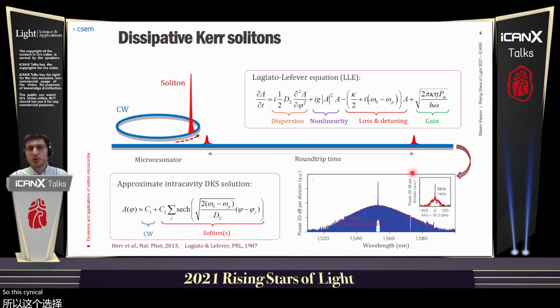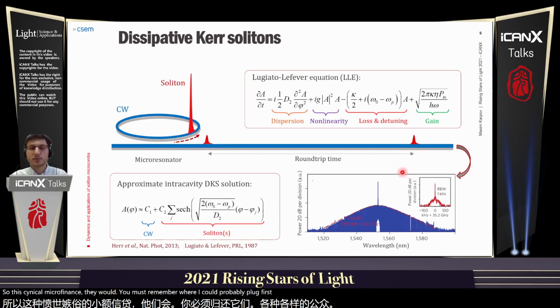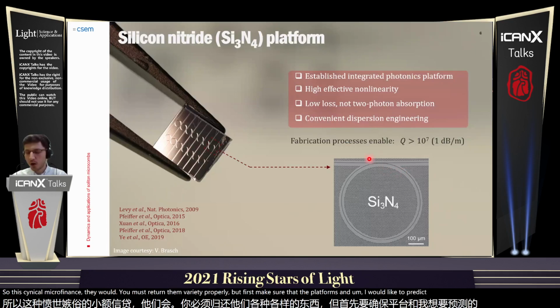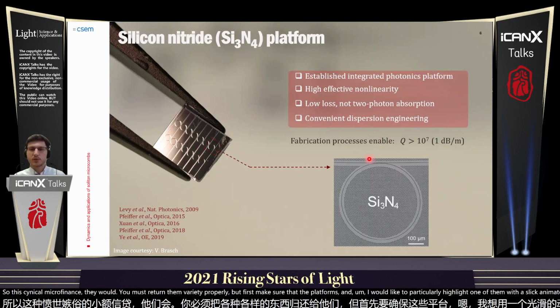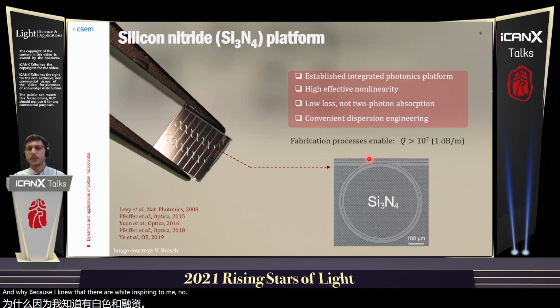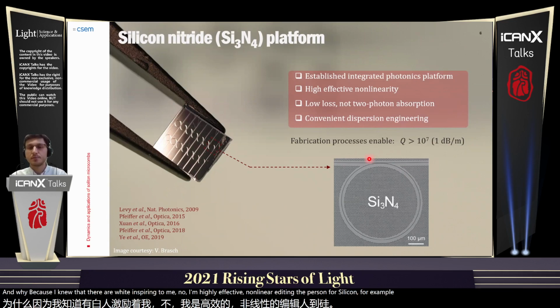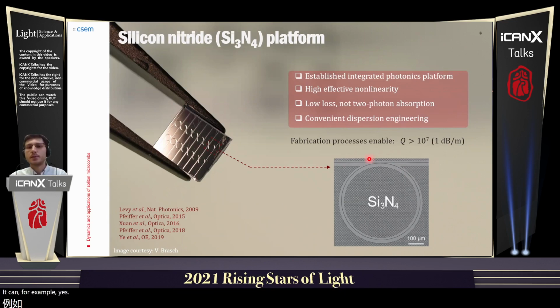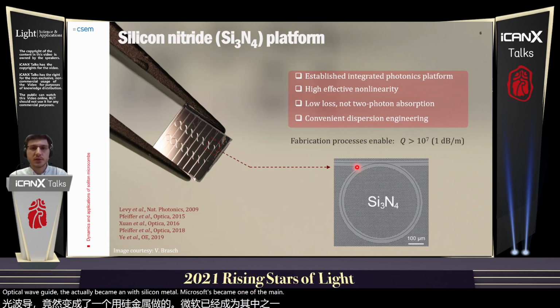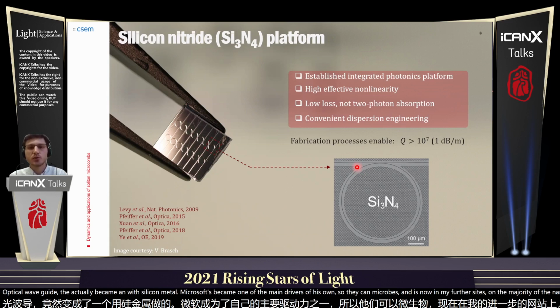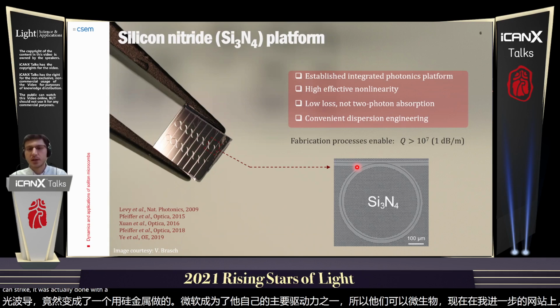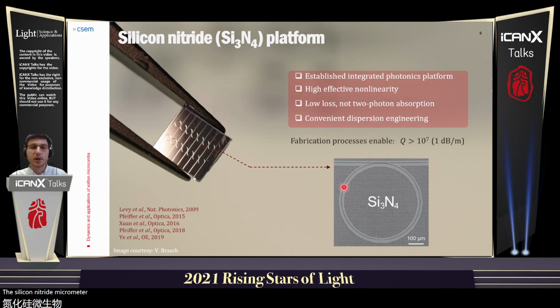So these soliton microcombs were demonstrated in a variety of photonic microresonator platforms, and I would like to particularly highlight one of them: silicon nitride microresonators. Why? Because of their wide transparency window, high effective nonlinearity in comparison to silicon, for example, combined with a fabrication process which enables very low loss optical waveguides, silicon nitride microresonators became one of the main drivers of soliton microcombs. And in my further slides, the majority of the dynamical effects and also the majority of the applications which we demonstrated were actually done with the help of these silicon nitride microresonator soliton microcombs.